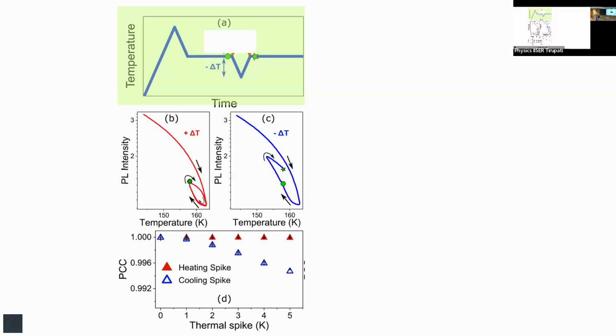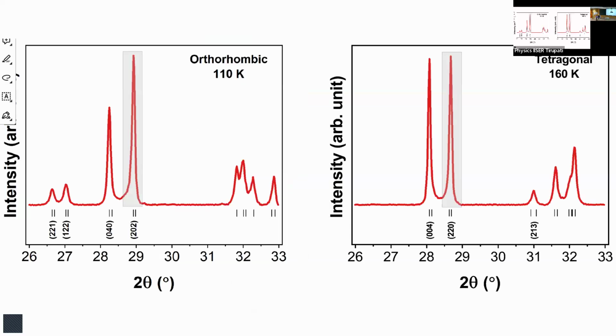So depending on whether I'm interested in the positive or negative spike to be detected, I prepare the initial state differently. Why does it happen? It happens all because of structure. The orthorhombic structure is given here and the tetragonal structure is given here. This one appearing at this angle and this one appearing at this angle. They're at 2 different angles. I'm going to take this part and expand it and show you. At 110 Kelvin, both cooling and heating curves show this orthorhombic peak. Heating and cooling, both are tetragonal, one on top of the other.